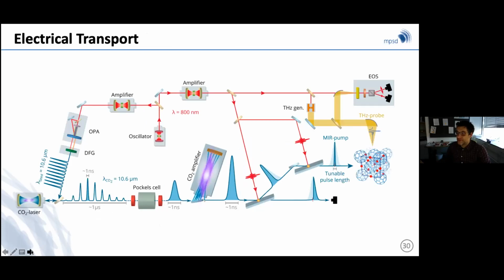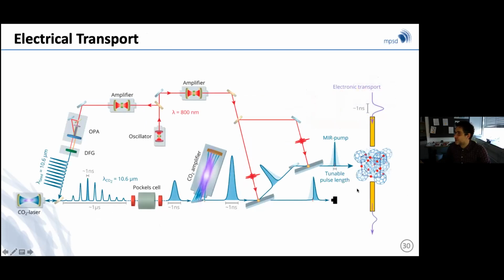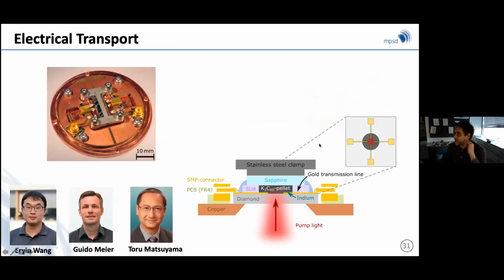And so what Matthias and Thomas did was to do the same experiment, but rather than using terahertz, doing electrical transport experiments. Turns out that with these powders it is not so straightforward. So there's a whole set of technical aspects that are required here to do these measurements. Again, with a lot of help by Guido Meier and Toru Matsuyama.